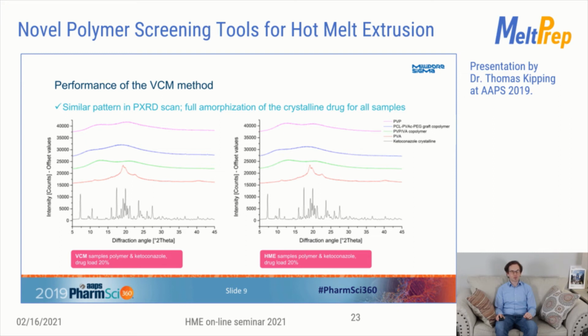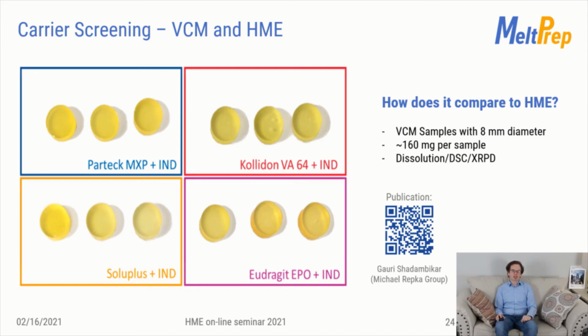This was already indicating that it's of great help for formulation screening. Based on this initial data, a comprehensive study was conducted by a PhD student of Professor Michael Repka. In this study, the model compound Indomethacin was used to investigate if hot melt extrusion and VCM yield similar results. On this slide are images of VCM samples with 8 mm diameter with some common carriers, including Parteck MXP. The samples went through intensive characterization, showing comparable data. The paper is open access and is linked on the QR code on the slide.